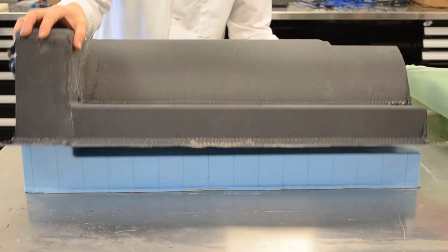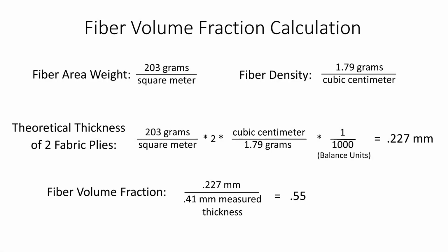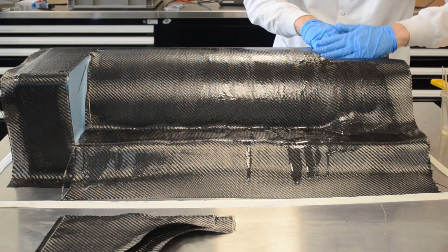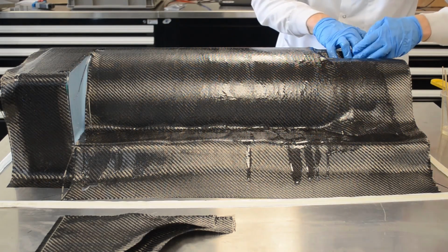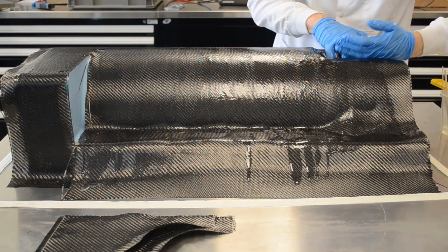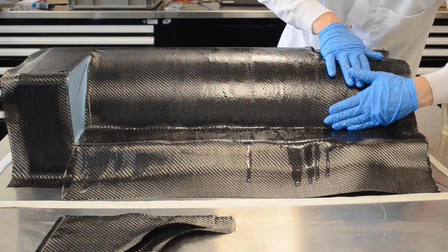After demolding the part, we can see that we had some fiber bridging in the corners. The fabric was not deposited all the way down into the corners or had been accidentally shifted after it had been placed. A fiber volume fraction of 55% was achieved. It is important to ensure that the working time of the resin is sufficient to deposit all fabric plies and accurately position the vacuum bagging consumables.